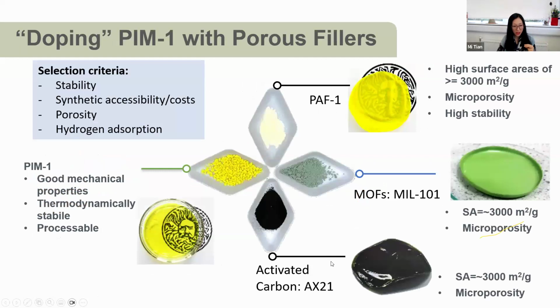So in order to improve its hydrogen storage capacity, we doped the PIM1 with different porous fillers, for example, one of the MOFs, and activated carbon. All those porous fillers have an extremely high surface area, around 3,000 square meters per gram, and also a small ideal pore size, less than 1 nanometer, good hydrogen adsorption capacity, and also stable. So doping PIM1 with porous fillers, we can combine the good mechanical properties and processability of PIM1 with the good hydrogen storage capacity of porous fillers as a composite.